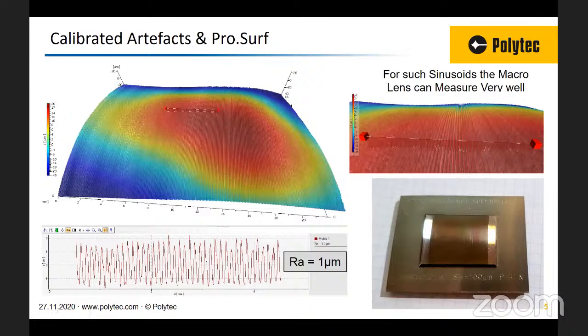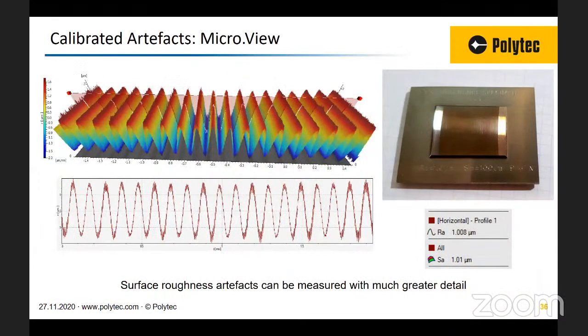So I've got some information here about calibrated artifacts. This first is an Ra 1 micron from a Rubert standard. The first measurement here is measured with a ProSurf S system, so a smaller field of view system. And of course, you can see that Ra equals 1 micron. You get a result. I then measured this same artifact with the MicroView. Now you can see much greater detail on this sinusoid. We can see the finer texture details. That's not noise you're looking at. That is the actual texturing of the surface. And you can see the sinusoid. And again, you can see that you're getting Ra and Sa in the order of 1 micron.